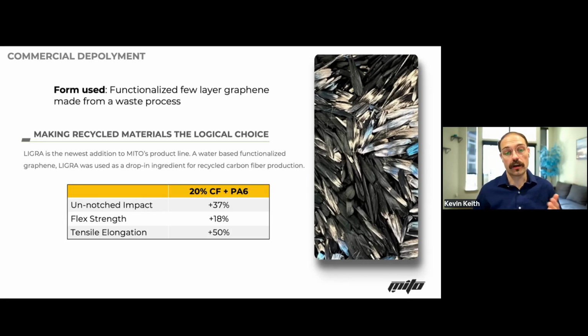So when it was sized onto the carbon fiber at extremely low loadings, less than 0.5%, then that fiber was put into a nylon 6 at 20%. So all in all, the graphene's weight by the total end composite was about 0.02, 0.03%. With just this product, we were able to increase the nylon 6 performance, unnotched impact by 37%, flex strength by 18%, and the tensile elongation by 50%.